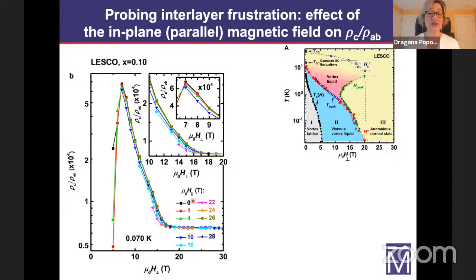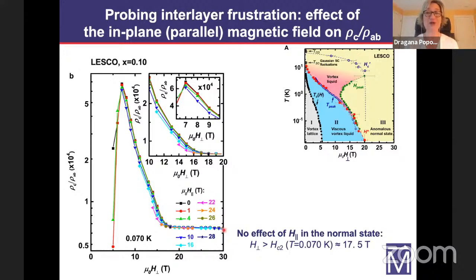And in addition, we have a parallel field component, or a magnetic field in the plane also, as given here. So first of all, what we see at the highest fields is that we do not see any effect of the parallel magnetic field, which supports our earlier conclusion that in this region there is no evidence from our experiments, at least, for a continued presence of Cooper pairs. So it seems that this indeed is the upper critical field.